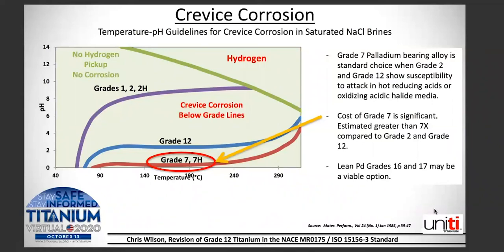As you can see here, that's the same chart I was showing earlier. Grade 7 palladium bearing alloys are the standard choice when grade 2 and 12 are susceptible to attack in hot reducing, oxidizing acidic halide media. So depending on what the environment is, you may need to go to a grade 7 or a palladium bearing grade. Now, when you look at it, the cost of the grade 7 with the palladium added is significant. It's estimated greater than 7 times compared to grade 2 and grade 12.